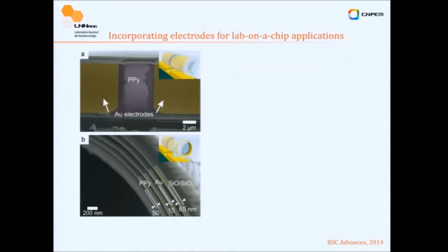So here's a cross section, you can see the polypyrrole thicker close to the contacts, so we cut the tube along it. And here's perpendicular. And if you look here, you have a quite fancy heterojunction, where you have metal, oxide, and polymer, and so on and so forth. It's a junction. If you try to do it by layer deposition, for instance, you cannot prepare it. And you can get it by rolling.